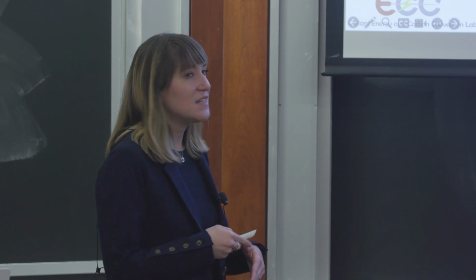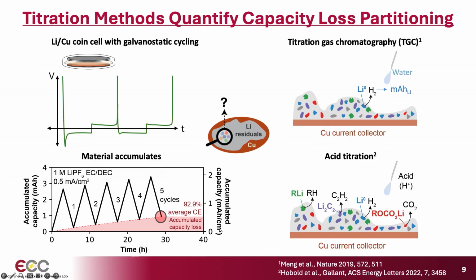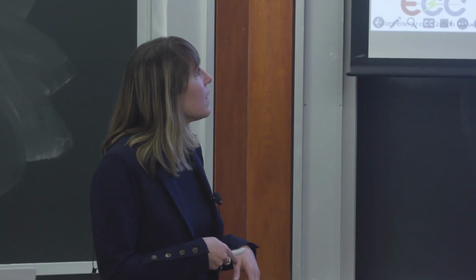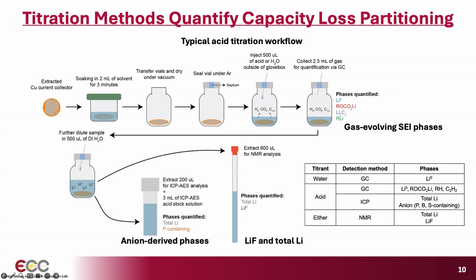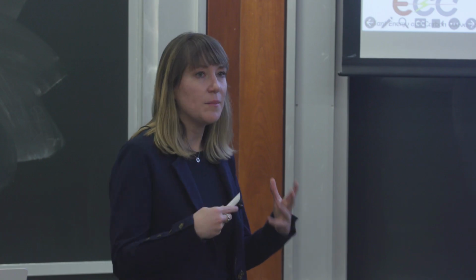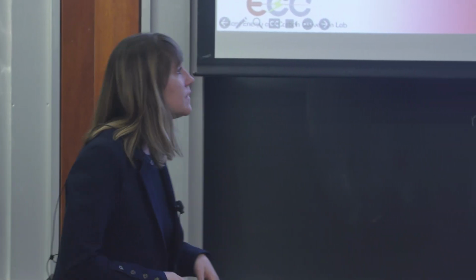We found that if you change the titrant to acid, you can start to get more information because there are many SEI phases that will be protonated by acid and evolve signature gases that you can then quantify. So we can start to get information on actually quite a diverse set of species in the sample. And once we've extracted the gases for headspace analysis, another nice thing about these acid titrations is it actually digests and dissolves the entirety of the sample, and there's more information we can glean by looking at the liquid that's left behind. So for example, we can quantify the total amount of lithium that was present in the sample. We can look at the amount of lithium fluoride that was in the SEI by NMR, and we can look at other anion-derived phases. So the point I want to make is simply that we can really expand our capacity loss attributions by switching the titrant.